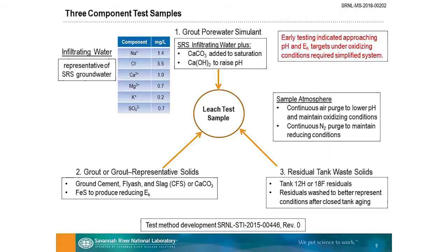We also, for the reducing cases, added ferrous sulfide to get the oxidation reduction potential down in the range or near the range that we were targeting. The third phase was the actual tank waste solids, either tank 12 or tank 18. We typically, although not in all cases, washed those solids with groundwater simulants because you can imagine over time the materials in the tanks are more washed than not washed. So those are the components of the simulants.